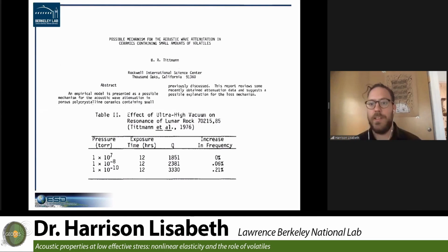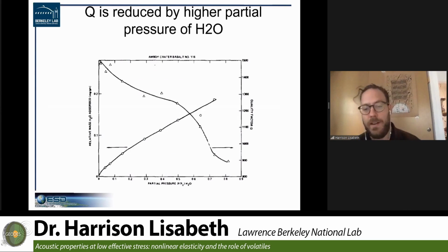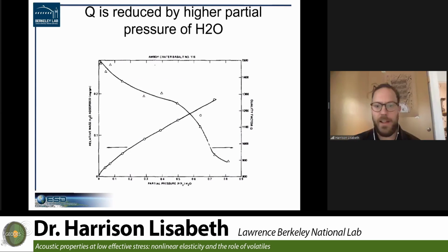He then went on to do a number of exhaustive studies of this phenomenon to try to understand what's going on, and studied the vapor pressure dependence of Q in the materials, and found that, in fact, at very low partial pressures of water, you have high Q, and then that reduces as you increase the partial pressure of humidity.